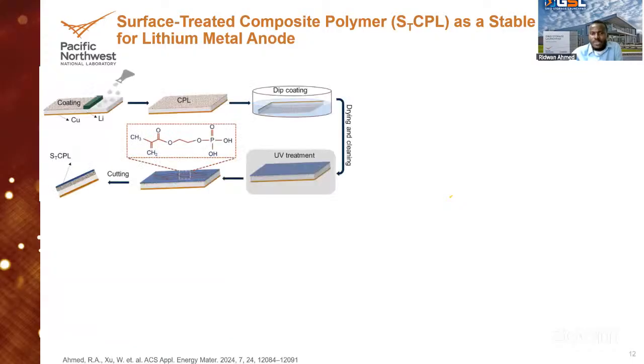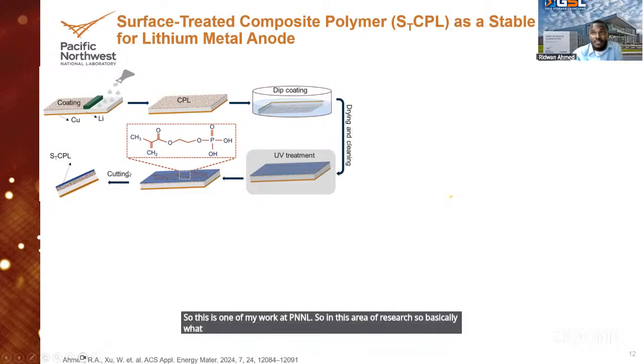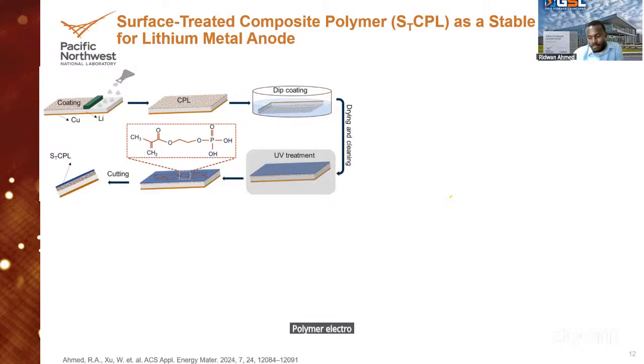So this is one of my work at PNNL. In this area of research, basically what we did is that we have this lithium metal, and we had this coating, which is a composite polymer, a combination of PEO, a commonly used polymer electrolyte, with LLZO. And so we have these composite coatings on the lithium.